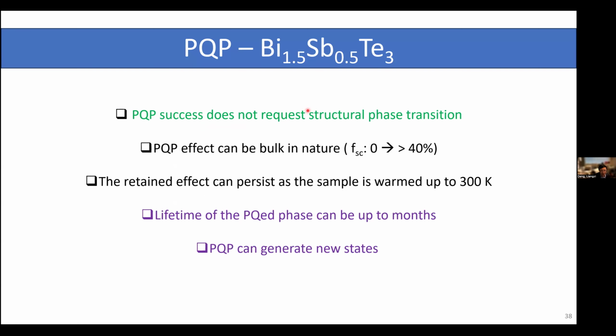So here we further prove that PQP success does need a structural phase transition in some cases, but doesn't have to depend on a structural phase transition. That really broadens the material base for us to apply this technique. And since we're able to recover the sample and then measure it in the SQUID, we are now more confident to say this pressure quench effect can be bulk. Maybe in some cases, I cannot guarantee that every time it's bulk, but at least this is a very strong example showing it could be bulk in nature, because going from non-superconducting to superconducting above 40%, that's very nice evidence. The other thing is regarding how robust it is.